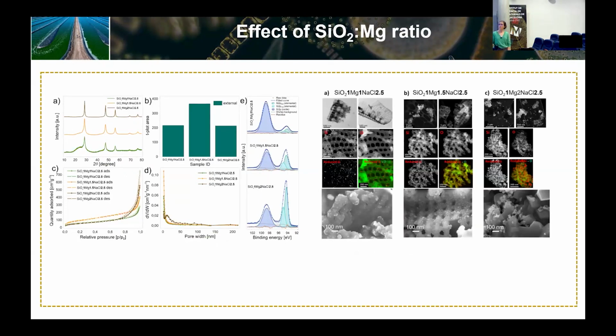This will be the case when you have a more silica-rich sample. This is the bump of the amorphous silica. And this is the situation where we have more silicon-rich SiOx. If you look at this, you will see that in the first two cases, particle morphology is preserved. We can see that silicon crystals are being grown at the surface of the silica.